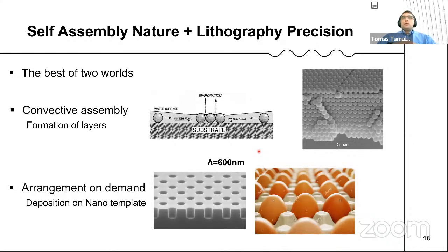So how to gain the most from those nanoparticles and the self-assembly? So why not to use the best of two worlds? Use this convective assembly, which forms layers from small particles, which is known, and apply a bit of lithography to define the positions that we want our nanoparticles to sit in. So we can arrange some nano templates, in this case like 600 nanometers, let's say. And what we expect is that the nanoparticles will sit in those pits like the eggs here in the box.